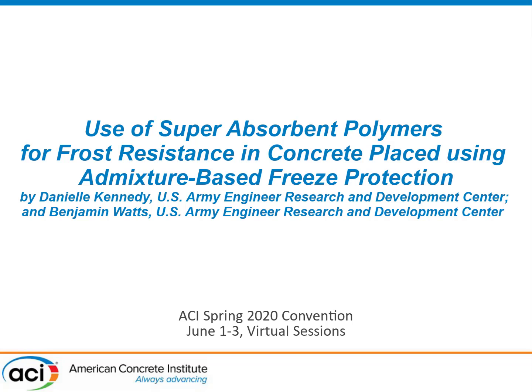And some applications for this, as I said, this is very niche. We are combining additives to place this in cold temperatures with SAP to be able to not have to use chemical air entrainment. So applications for this would be, you're in a cold environment, you have a patch on, I don't want to say specifically a runway or a roadway, or just wherever you'd have a concrete placement, maybe a slab where you don't have time to wait and it needs to be placed and it's already cold temperatures, it's below freezing, and you also don't have the means or the time to test a bunch of different sample mixtures to get your air entrainment perfect with a typical chemical air entrainment, and that this SAP could be used in place of that. So again, a very specific